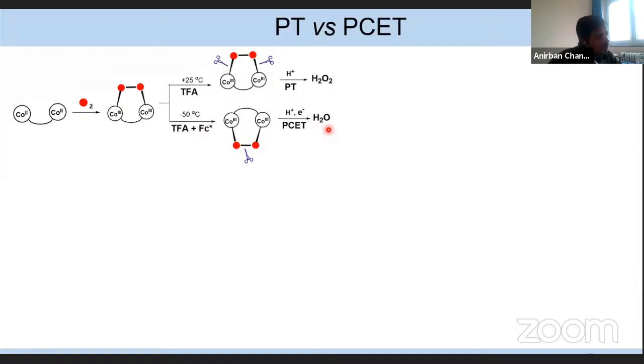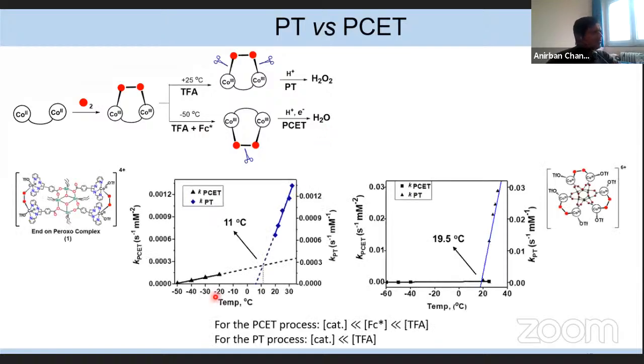And I determined some more proton transfer rates and proton coupled electron transfer rates at different temperatures. So for the tetranuclear complex, at low temperature, you can see PCET is the predominant factor, as I showed here. Whereas at high temperature, proton transfer operates very drastically. And the transition temperature I experimentally observed is 11 degrees centigrade. Whereas for the hexanuclear cobalt complex, the transition temperature between proton coupled electron transfer and proton transfer process is around 20 degrees centigrade.